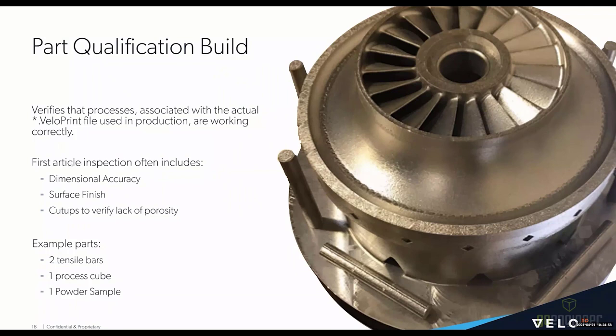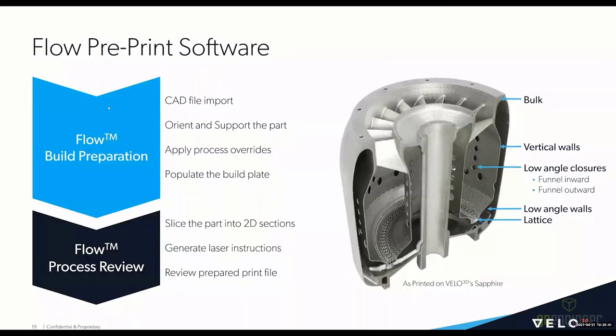And really at the end of the day, this is basically a first article print. So similar to standard first articles for conventionally made parts, you have dimensional accuracy, surface finish, and cutups as well to verify lack of porosity. Cutups are common as well the first time you have a forging or a casting, and it's similar here. Additionally, with each part, generally there's two tensile bars, a process cube, and a powder sample that are taken at the same time, just to verify quality of build, that are added on.